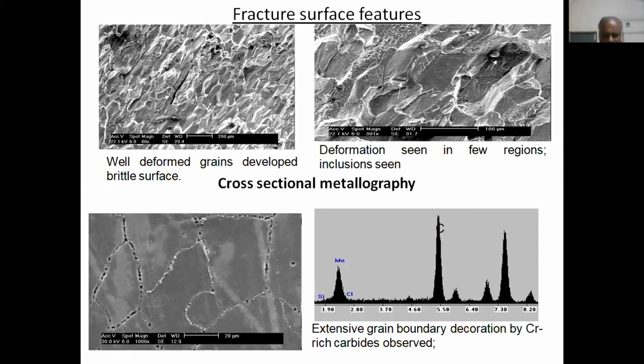I think Dr. Matthew or they mentioned energy dispersive X-ray analysis in SEM. You can easily understand the microchemistry of the precipitates and find that it is rich in chromium and molybdenum. That means these precipitates are sitting there, and under this condition, if you deform or do cold pilgering, it will only end up in the fracture of the tube, whatever you are trying to manufacture. So how to avoid this? You should make these precipitates go into solution. How to do this? Go to higher temperature and do a hot forming operation. Then you will be able to do a good extrusion or a pilgering operation without a breakage. So this is the recommendation.